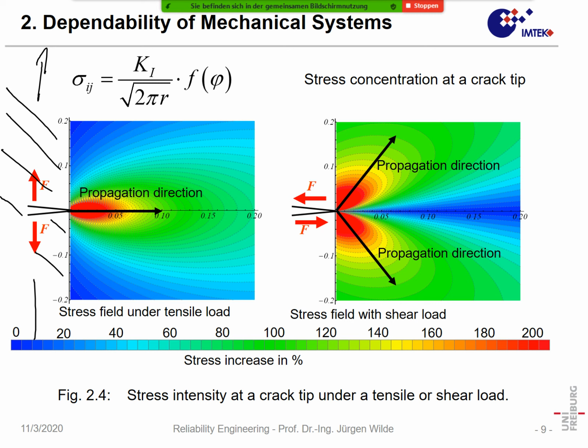We can have different loading. For instance, that is tensile loading. So we have this increase of stress. On the other hand, when we have a so-called shear loading, so above and below the crack or notch, it is shifted in different directions. We have two maxima under different angles. But what we can also see is that the stress increase is very high. It can be more than 200% compared to the average stress here.